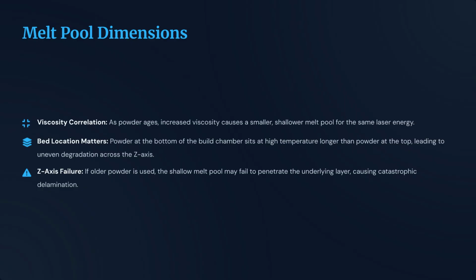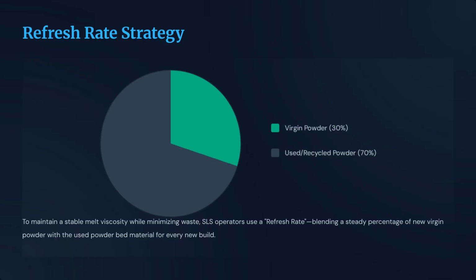Because powder degradation varies by location in the build chamber, Z-axis performance can suffer. If older powder is used, the melt pool may become too shallow to properly bond with the previous layer, leading to delamination. To manage this, operators use a refresh rate. By blending a specific percentage of fresh virgin powder with used material for every build, they maintain consistent melt viscosity and extend the usable life of the powder supply.